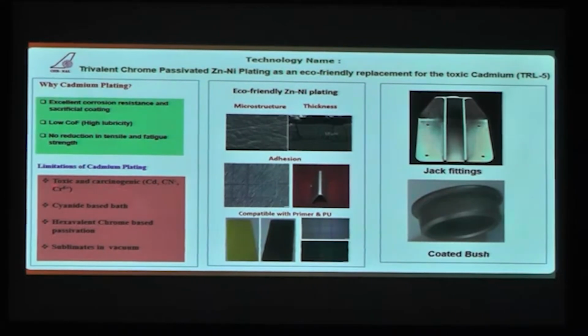But unfortunately, it is toxic and carcinogenic because we use cadmium in the process. There is also cyanide in the process and also hexavalent chromium. All these three entities are very carcinogenic and have to be limited. So we have developed an alternative, the zinc-nickel process, and it has been evaluated extensively as per the AMS standards, and its thickness is in the range of 10 to 14 microns.